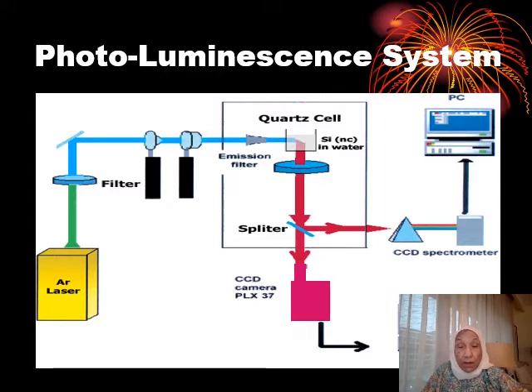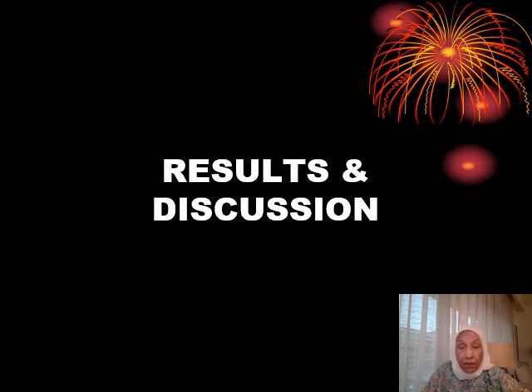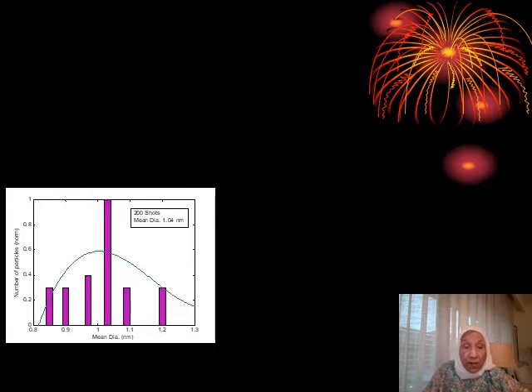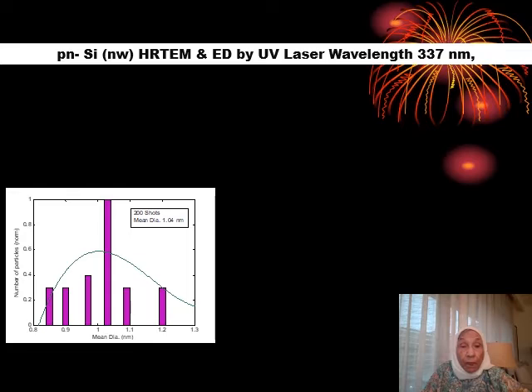So these are our results. I will show only 3 types which have been recorded according to the PN silicon nanowires: high resolution transmission electron microscopy, to count the number of particles formed, and electron diffraction, to determine whether they are crystalline or not. And we used, of course, the UV nitrogen laser, with the wavelength 337 nanometer, to ablate the silicon PN sheets.